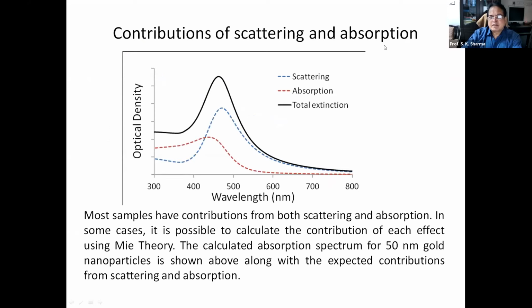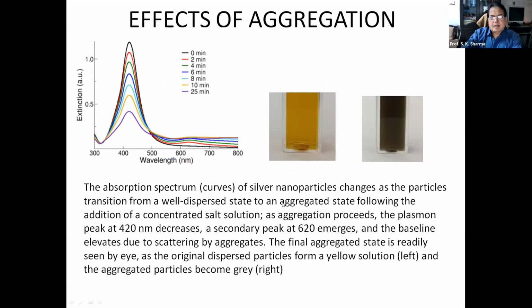And then you have the contribution of scattering and absorption. So you see total extinction is there, optical density is there. How they combine gives the total extinction of this optical density, like this. And aggregation effects are also there. The way I told you that we record the spectrum with time. So with time aggregation is taking place in the solution, meaning some kind of precipitation is taking place, like when we form cottage cheese from milk. The milk particles start combining with each other to form the particles of the cheese. So there is aggregation taking place, and the size of those particles is increasing.